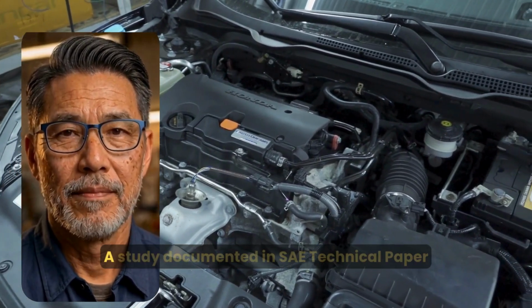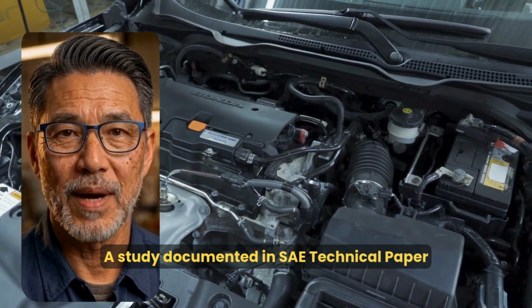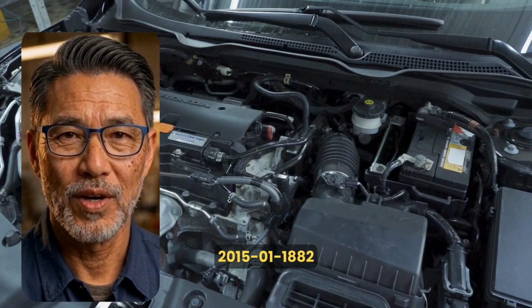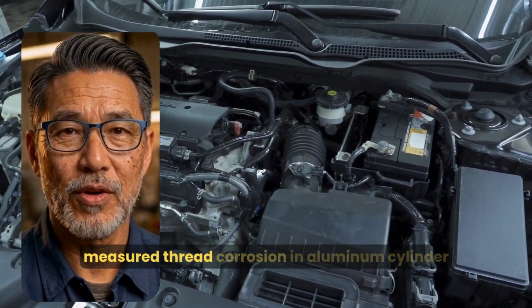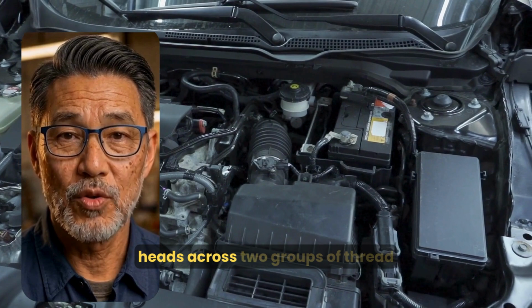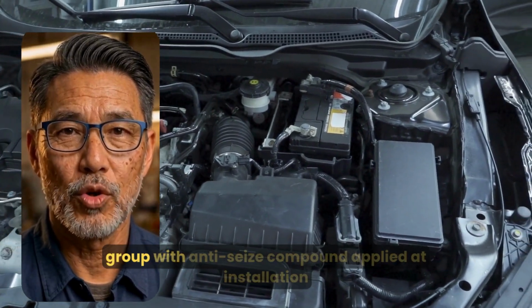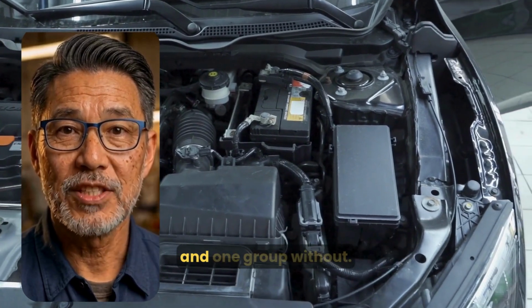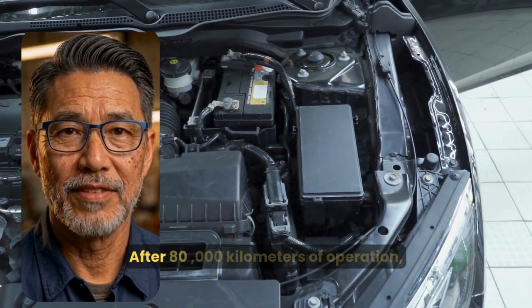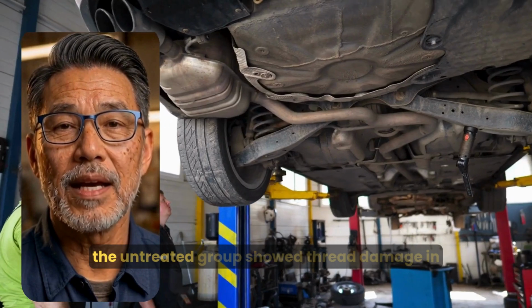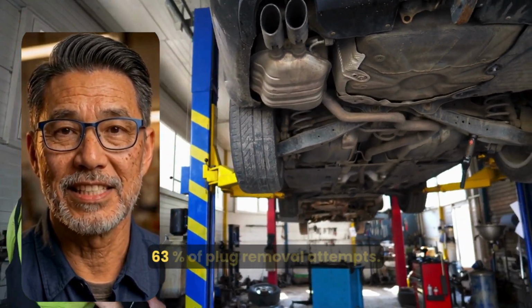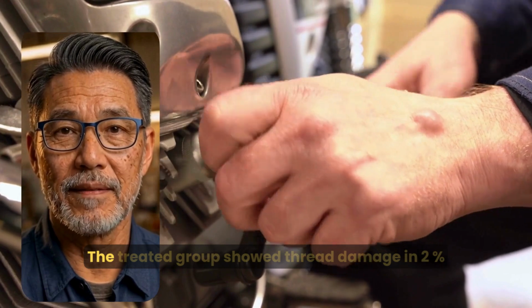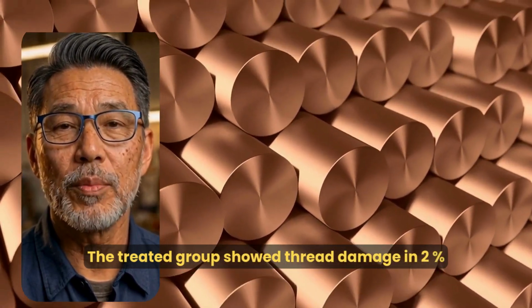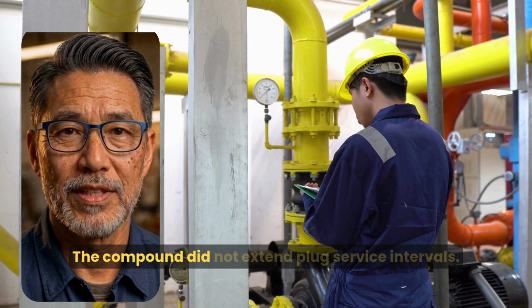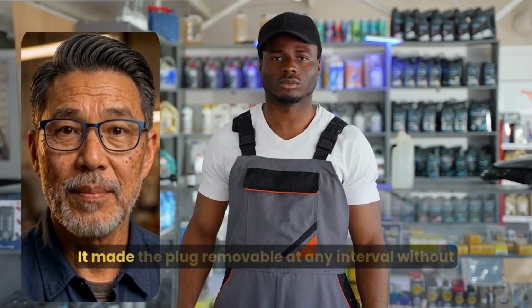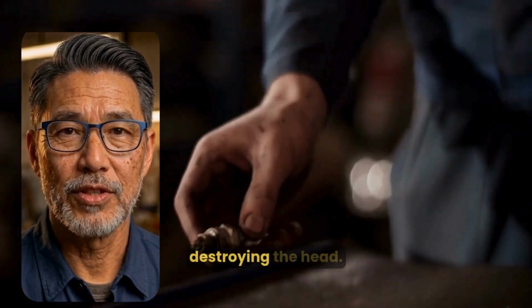A study documented in SAE Technical Paper 2015-1-1882 measured thread corrosion in aluminum cylinder heads across two groups of vehicles. One group with anti-seize compound applied at installation and one group without. After 80,000 kilometers of operation, the untreated group showed thread damage in 63% of plug removal attempts. The treated group showed thread damage in 2% of removal attempts. The compound did not extend plug service intervals. It made the plug removable at any interval without destroying the head.